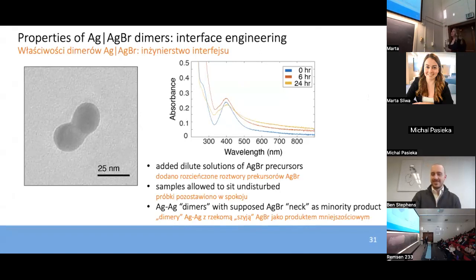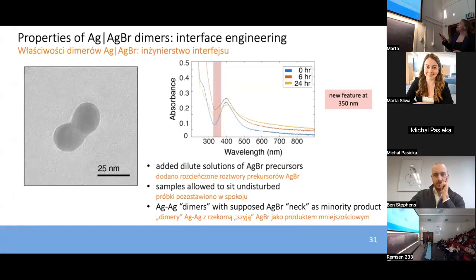Okay, so after we added those dilute solutions, we saw in less than 30% of the sample yield these silver-silver dimers joined by what we think is a silver bromide neck. And although they make up less than 30% of the solution, we still saw some differences in the UV-vis profile of these samples. And it's interesting to note here that these absorbance profiles feature a peak that is blue shifted or at higher energies compared to that silver plasmon at 405 nanometers. So this is expected for two plasmonically active metallic nanoparticles that are in close contact. According to plasmon hybridization theory, when you bring two plasmonically active materials in close contact, their plasmons hybridize or combine to form these higher energy hotspots in those interparticle regions.